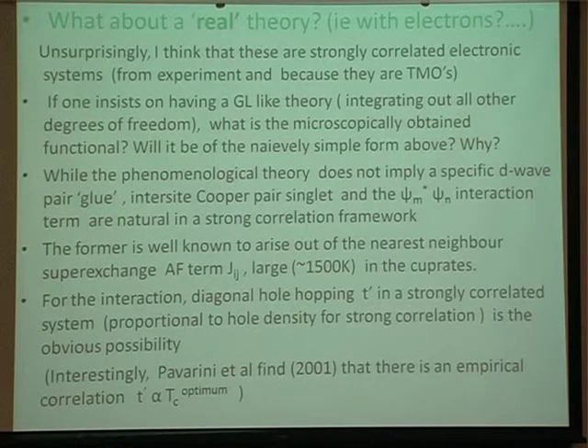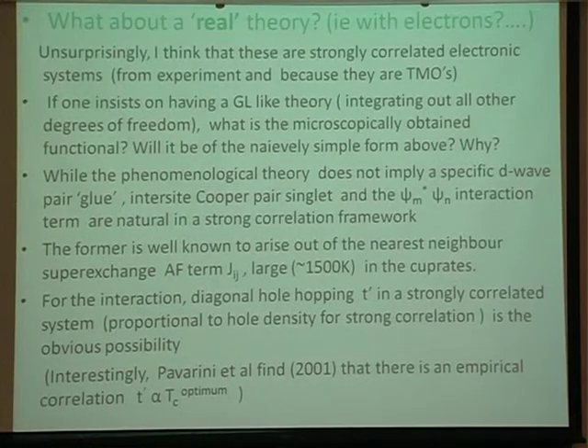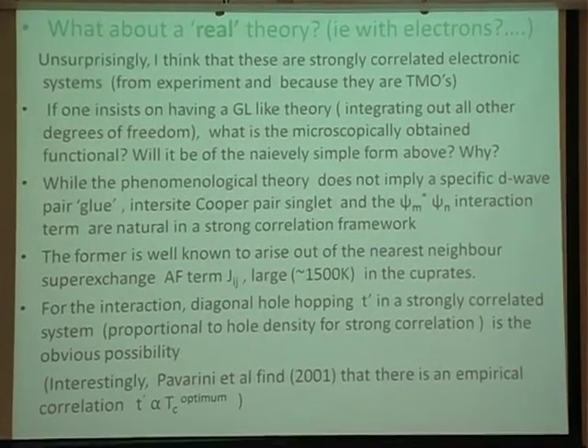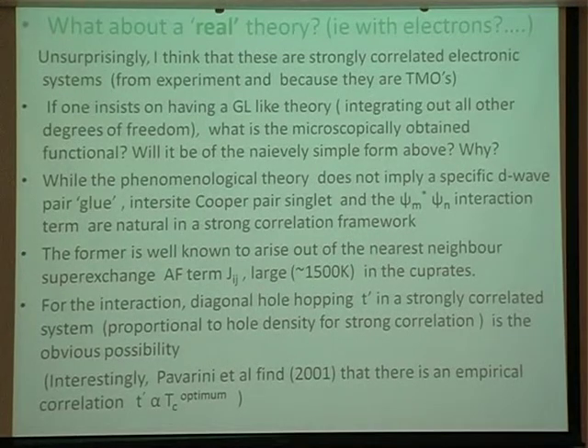So I just want to mention 2 things which seem to suggest to me that if we have a real theory involving electrons, that is more likely to be a strong coupling theory than not. The first is the fact that we know that there is experimentally a very large antiferromagnetic superexchange coupling, at least at 0-hole doping, which is surprisingly large. And it is also well known that this is exactly equal to nearest neighbor Cooper pair attraction.